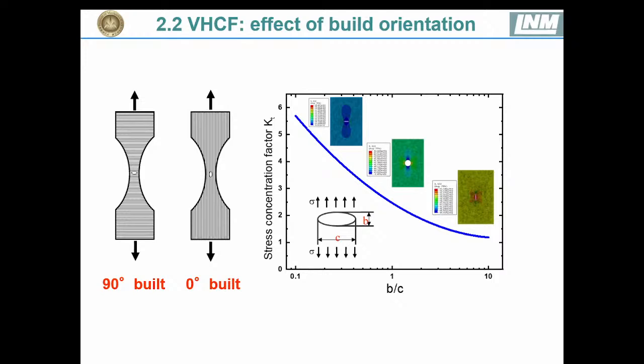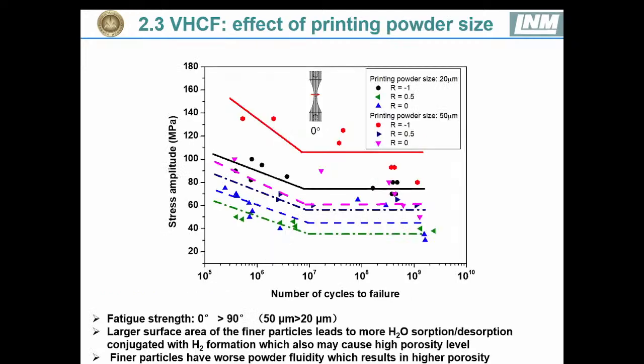Here, for the zero-degree build specimen and for the 90-degree build specimen, we can see that they show different morphology, and here the stress concentration is different. We calculated the stress concentration factor and demonstrate the difference between them. Here we see that for the 90-degree build specimen, the stress concentration factor is much higher than for those built horizontally. And this also explains the effect of building orientation on fatigue and also on tensile strengths.